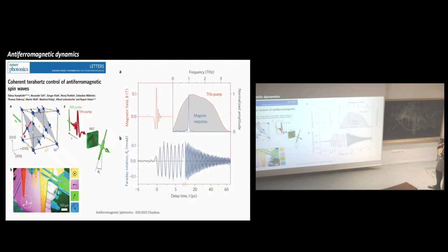And what they are doing here, you have the terahertz magnetic pump, which has a broad spectrum, typically from 100 gigahertz to a bit more than 3 terahertz. And then with the second pulse, they probe the dynamics, and this is what you see here. You see very nice oscillation at 1 terahertz. And if they Fourier transform this, then you see the magnon response of the NiO sample.